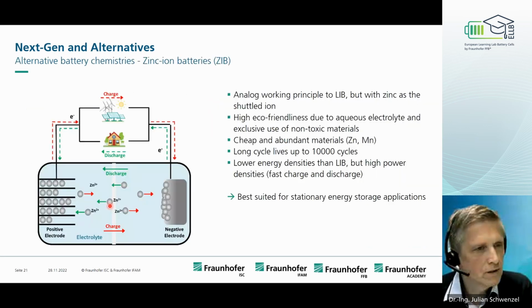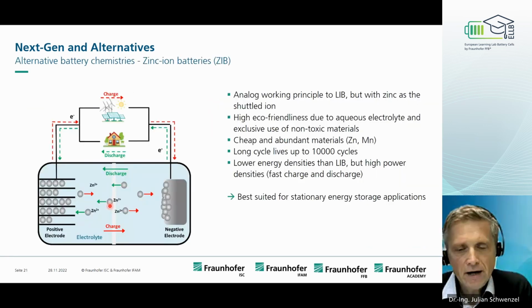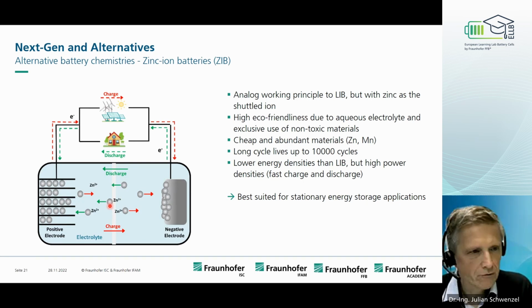And I would like to give you three views here. Maybe one alternative will be the zinc-ion batteries. The zinc-ion batteries work on the same principles as lithium-ion batteries, but here it is not the lithium ion, it's zinc ions shuttling between the anode and cathode. The zinc is very eco-friendly because we can also use an aqueous electrolyte. It's very cheap, non-toxic, and available, this material is abundant. They also showed very high cycle stability, 10,000 cycles is shown in some publications, but it's a lower energy density because zinc is heavy compared to lithium, but it's a high power density.